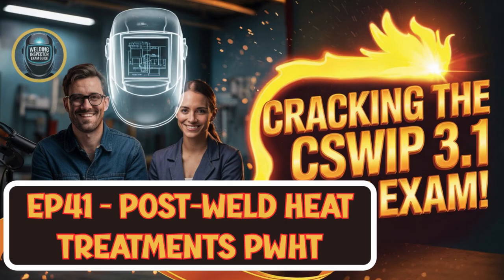Number 3 is the minimum time at soak temperature, also called the soak time or hold time. The idea here is pretty simple. You need to make sure the entire thickness of the weld joint reaches that target soak temperature and stays there long enough for the magic to happen. Heat takes time to travel through metal, so the thickest section of the entire welded item dictates how long that minimum soak time needs to be. You need to guarantee temperature equalization right through the core. Makes sense. Is there a rule of thumb for that?